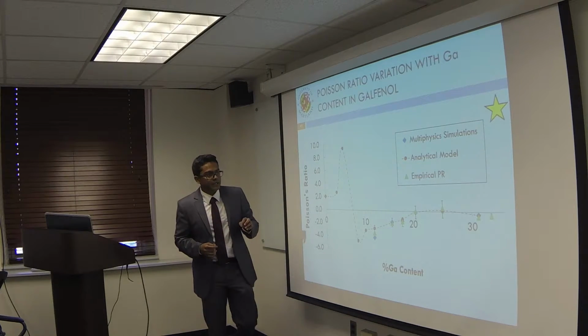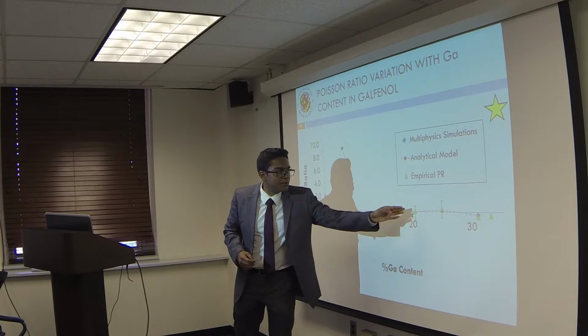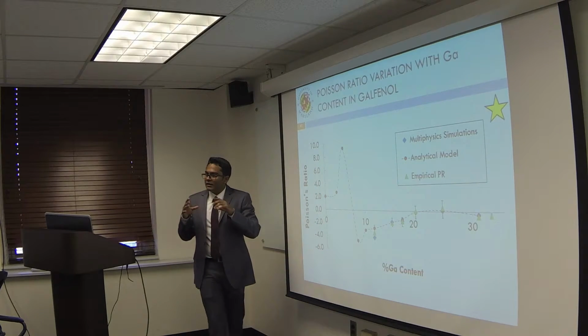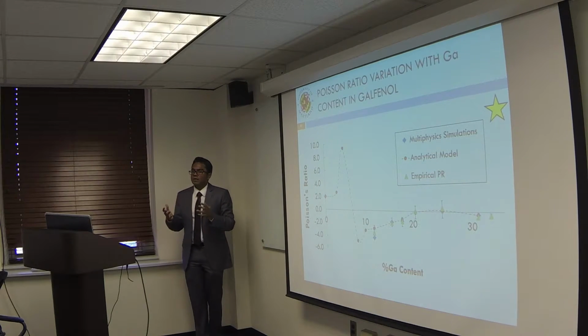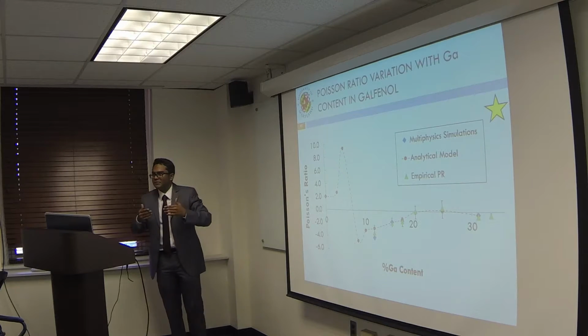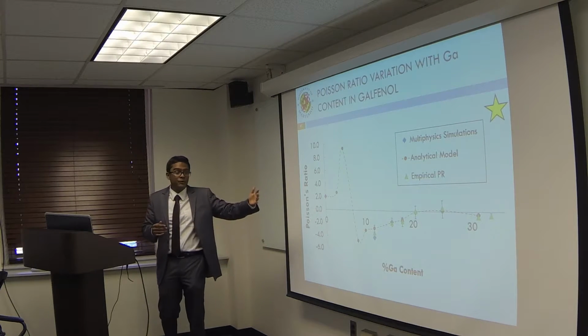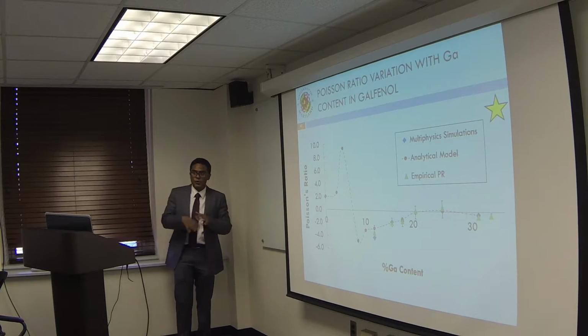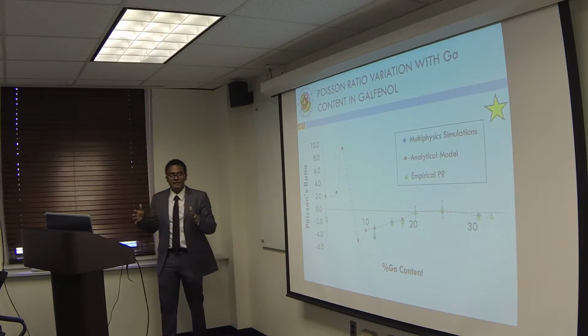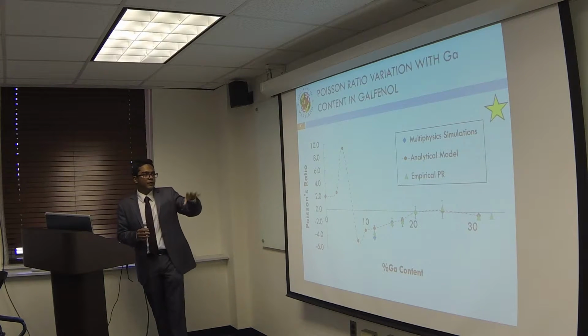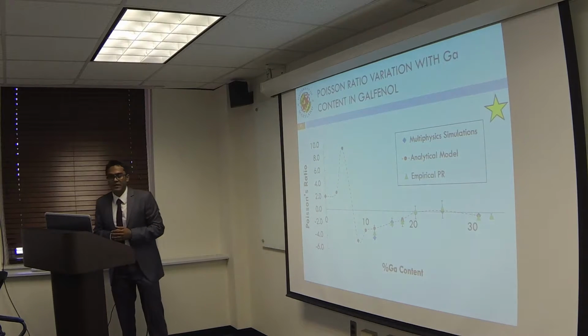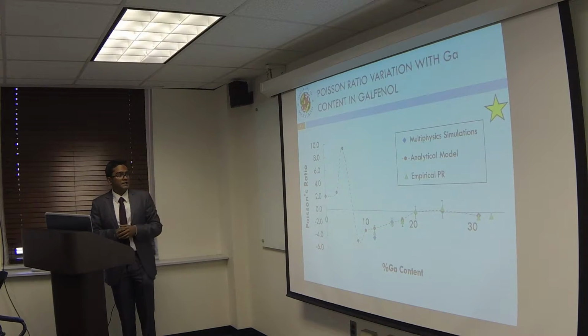But what's important is that in samples between 20 and 25%, the values of strains were so small that they were very close to 0. And sometimes because of drift, I was seeing values that were positive. So because I was able to do so many cycles and so many trials, I was able to come up with good error bars for the values that I obtained for Poisson's ratio at magnetic saturation.